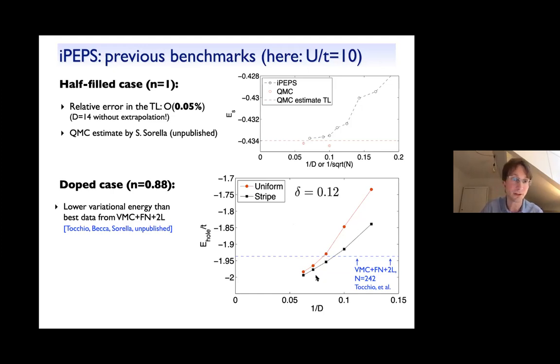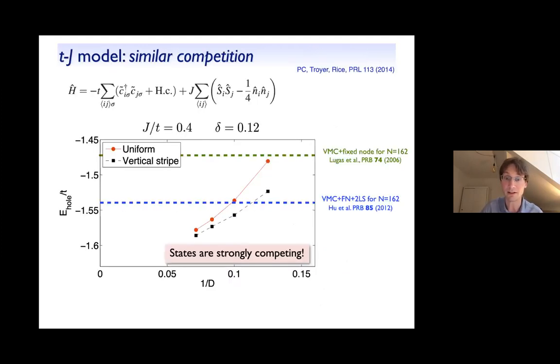And as we increase the bond dimension, things don't seem to get better here, but they're actually even more strongly competing. And that's something we already observed earlier in the TJ model, which is the effective model of the 2D Hubbard model. That was worked on together with Matthias Troyer and Maurice Rice. The TJ model you obtain from the Hubbard model using second order perturbation theory in T over U. So you neglect doubly occupied sites, but then the spins are interacting via a Heisenberg interaction.